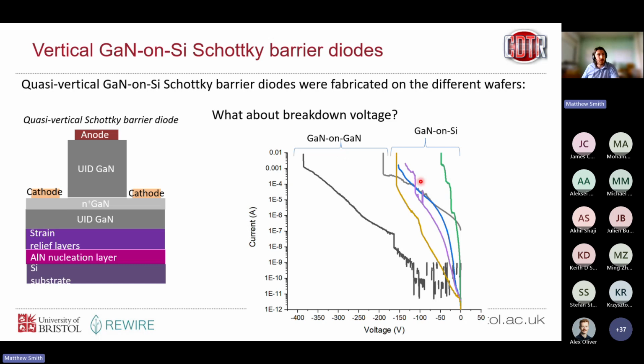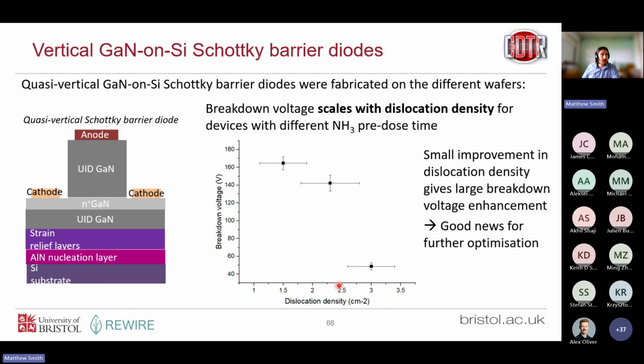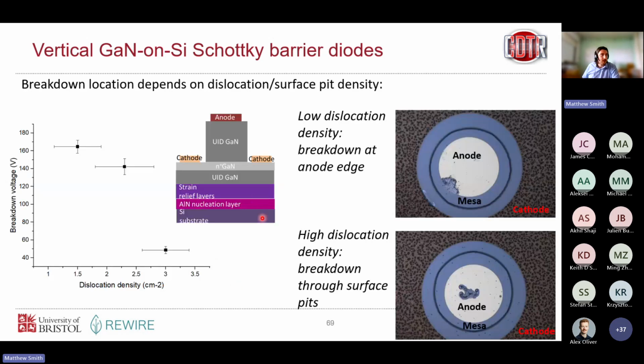In terms of our breakdown voltage, though, we do see quite a range. So this is that fairly well optimized GaN on GaN device with the mesa edge termination, and these are our GaN on silicon structures here. So breakdown all the way from sub 50 volts up to around 150 volts. And what we find is that there is reasonable scaling with dislocation density. So as we reduce our dislocation density, our breakdown voltage goes up, which is what we would expect.